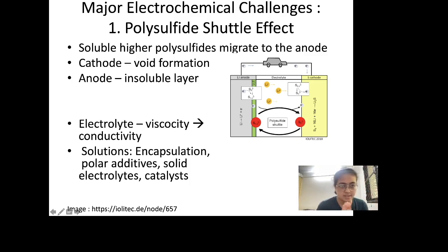So getting to the first one, which is the polysulfide shuttle effect. Essentially what happens is that the sulfur cathode gives out sulfides. The cathode, being the reducing electrode, reduces the sulfur to form higher polysulfides, which are very soluble in the electrolytes of the batteries, and those migrate to the anode side of the battery. So this is shown here, where these Sn2- go to the anode side, and of course the anode, being the oxidizing electrode, then oxidizes these higher polysulfides to lower polysulfides, and then they go back to the cathode. So they sort of shuttle back and forth, and that leads to more problems.